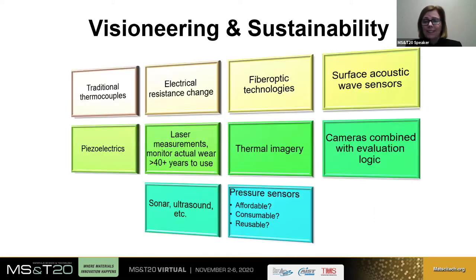The refractory failing isn't necessarily a problem. Not being able to predict the failure is. I've worked with some open innovation companies to try to identify potential candidate sensors. Many fell into the bleeding edge or leading edge category. This also means cost is an issue. And in refractory applications, you typically do not expect to reuse a sensor if it's embedded in the lining.